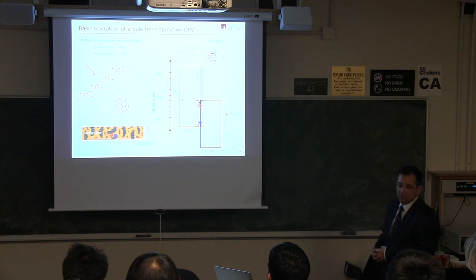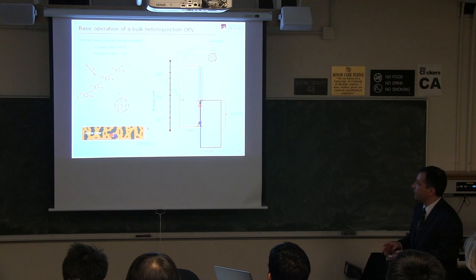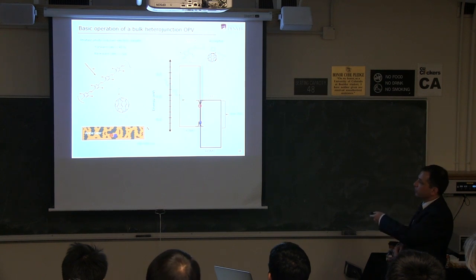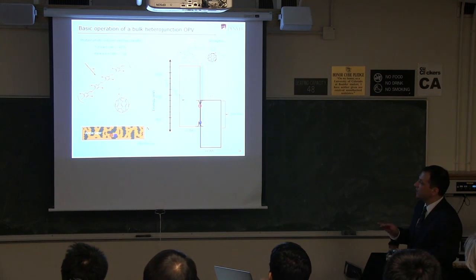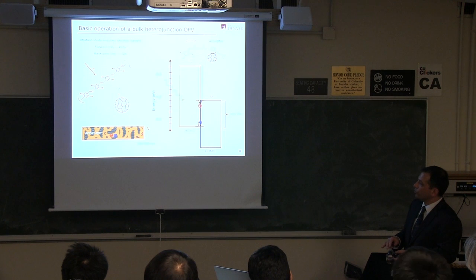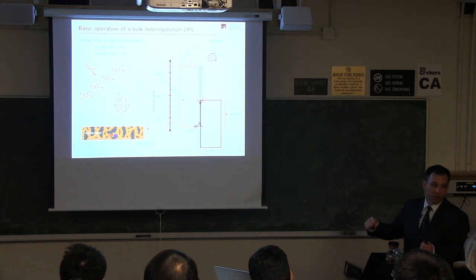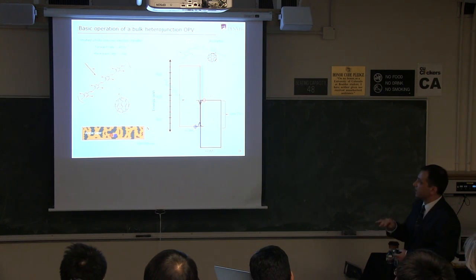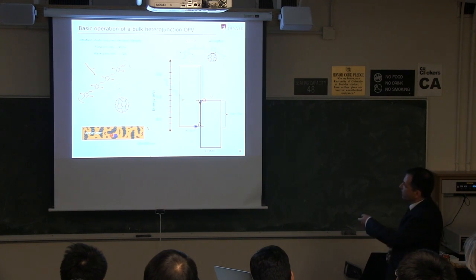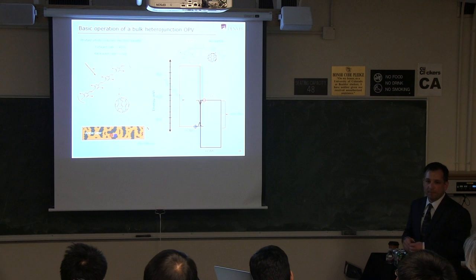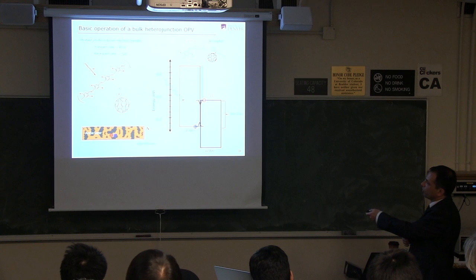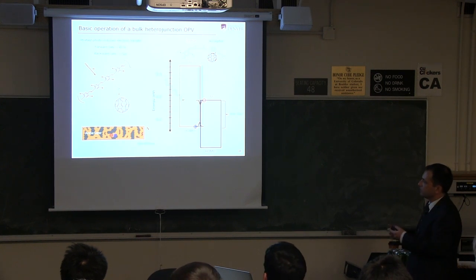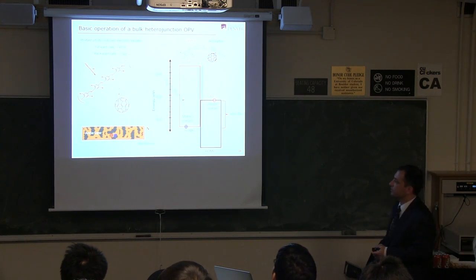Now, what happens is there's an intermediate state that I'm going to talk a lot about called the charge transfer state, which is kind of this little hiccup state before we get to full separation of charges that are mobile in the device. And it turns out that the CT state, the charge transfer state, is very important. But at any rate, once we have free charges, then we can rely on built-in fields inside the device or some selectivity of electrodes that would be attached to the hole side and electron side of the device and extract the charges out of the device.